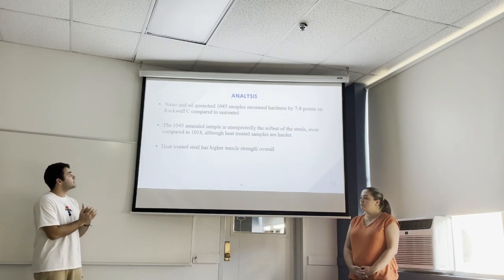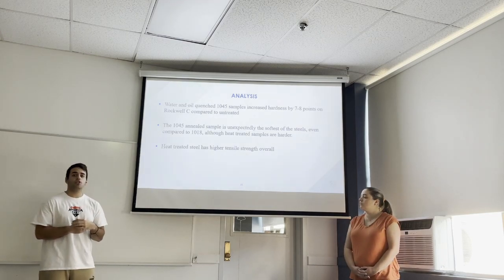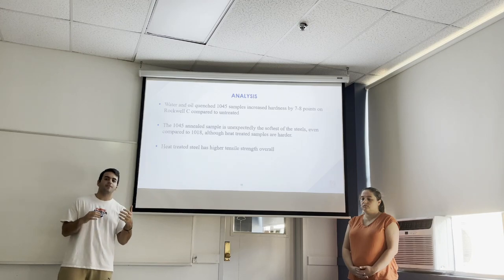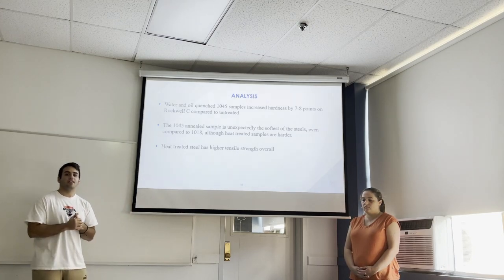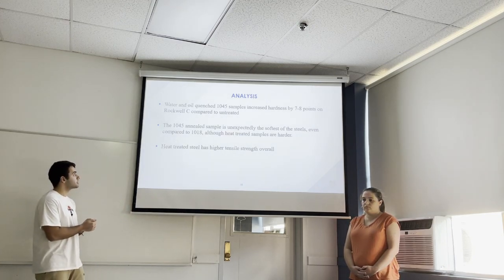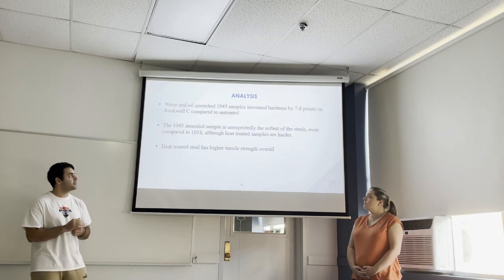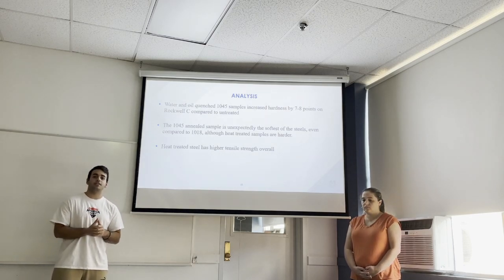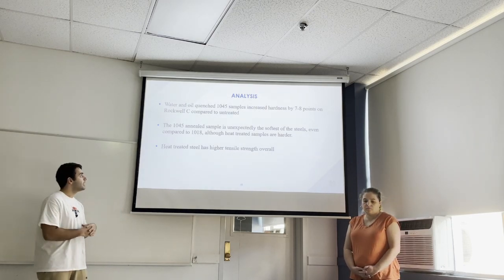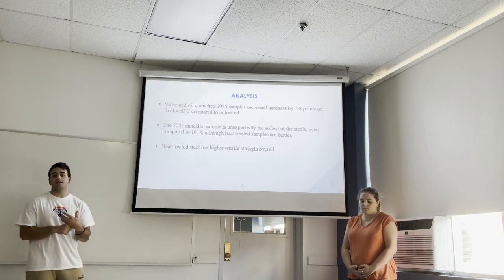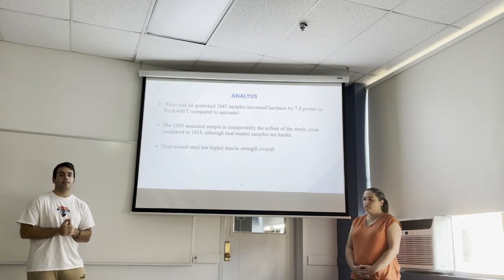Overall, our total analysis is that the water and oil quenched 1045 samples range from 7 to 8 points harder than the untreated samples. Again, the 1045 annealed sample is the softest of the steel samples, softer than 1018, and the heat-treated steel has a higher tensile strength than the non-heat treated.